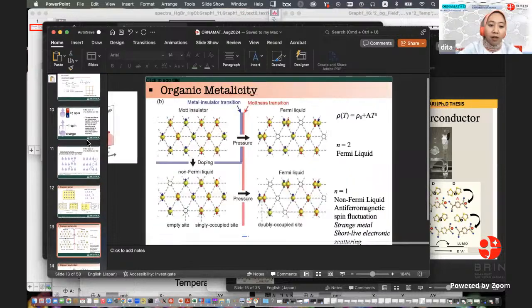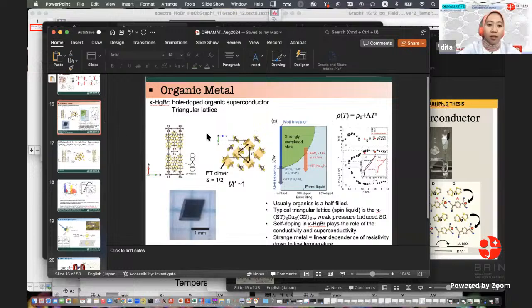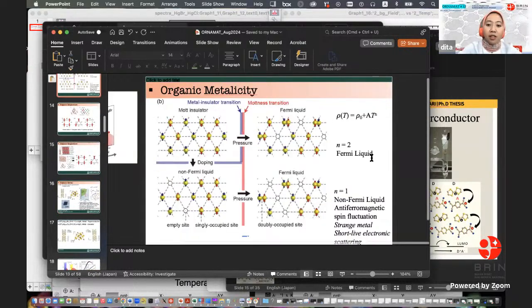Yes. The clear deviation comes from the temperature dependence of resistivity. As we know, we have other terms, like higher terms of the temperature dependence, maybe coming from phonons and so on. But the second term here is important to distinguish the typical Fermi liquid. The T square is the typical Fermi liquid temperature dependence of the resistivity for Fermi liquid materials. But for example, it was first found in the high-Tc cuprates, the inorganic superconductor.